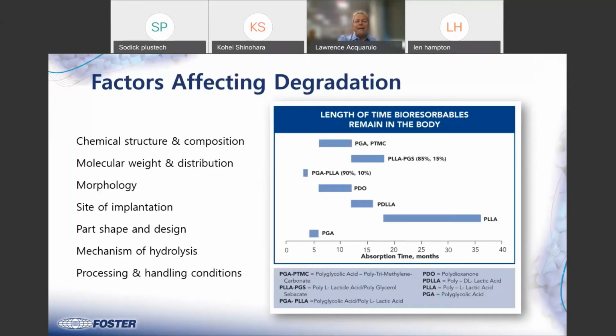So what are some of the factors that affect the degradation other than the polymer? Well, it's certainly the polymer itself, but molecular weight and molecular weight distribution play a huge role. The manufacturer usually has a range of molecular weights for that particular polymer, but in the processing and handling of it, when we do the compounding or blending, we have to pay careful attention that we don't knock down the molecular weight too much. And even in the extrusion of a tube or a fiber, or if you're injection molding a part, you want to make sure that you're not knocking down the molecular weight.